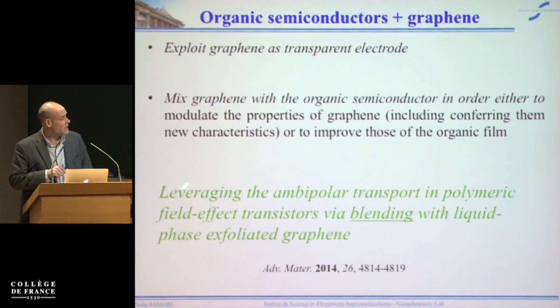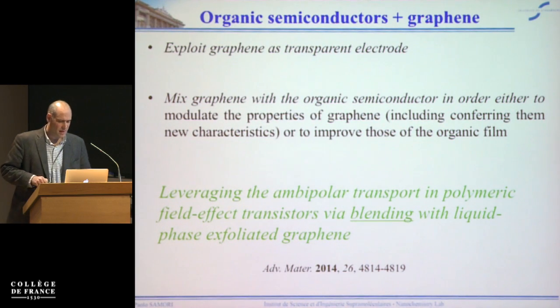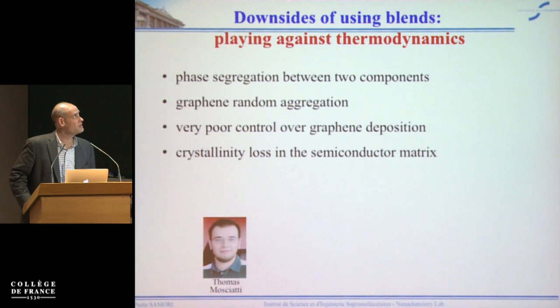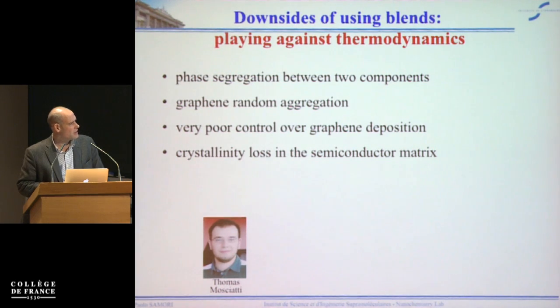And so the idea was something that we tried here and published in 2014, was that by blending we could leverage the ambipolar transport in a polymeric field effect transistor of a given organic molecule that was otherwise purely p-type. Now, the blending is nice, but has some downsides. The downsides are that you have phase segregation between different components. You can have random aggregation of graphene here and there. You have no full control over the graphene deposition, and you have a loss of crystallinity in the semiconducting matrix that would actually be a pain in terms of charge carrier mobility within the device. So this was the PhD work of Thomas Moschatti.